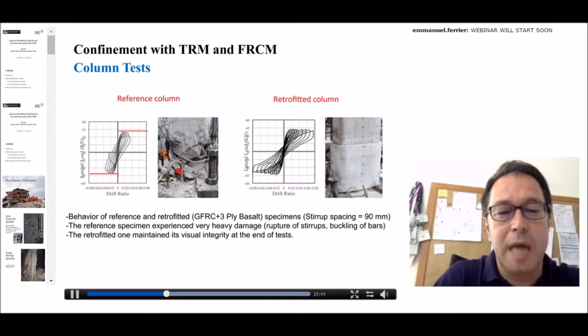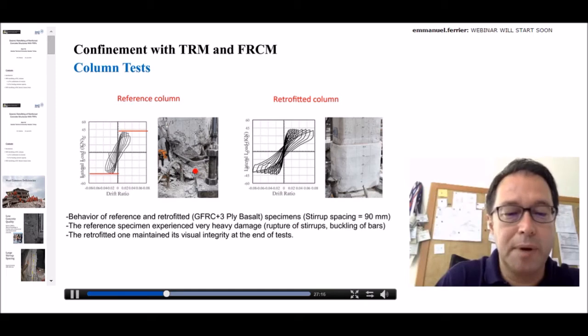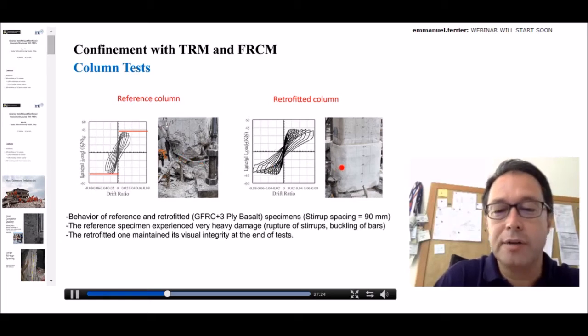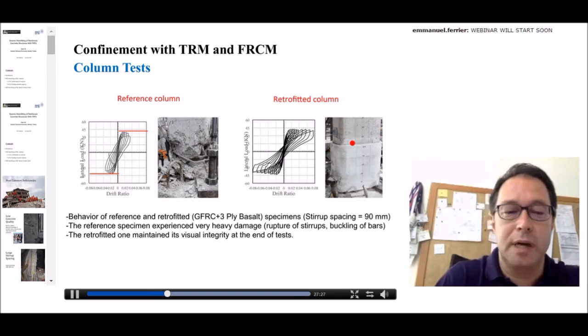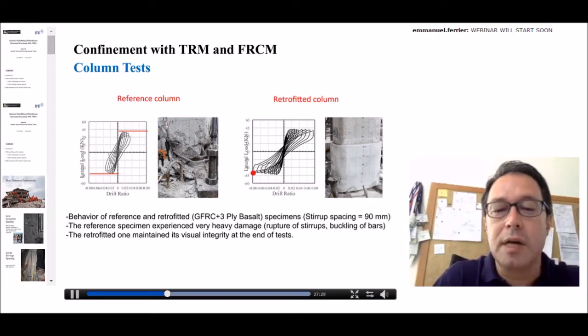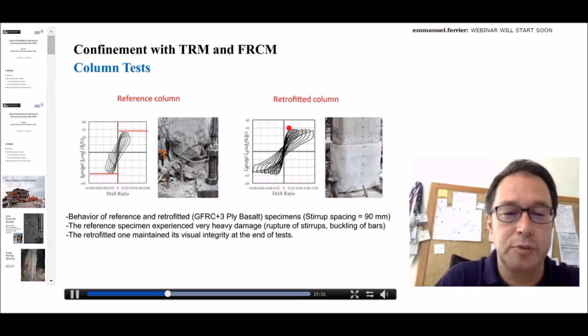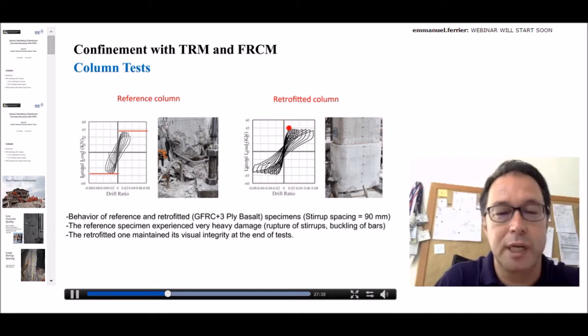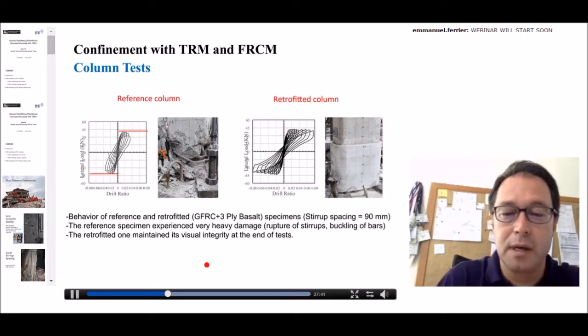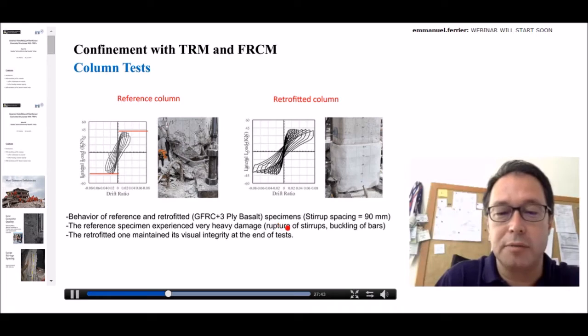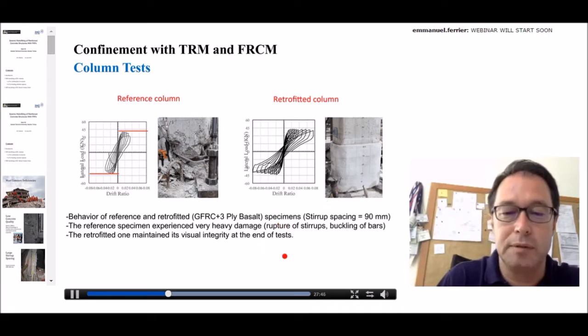So I think I already described the damage of reference specimens with rupture of stirrups, buckling of main bars, and total demolition of concrete after loss of this transverse reinforcement. On the other hand, this specimen retrofitted with this kind of jacket maintains load resistance capacity up to somewhere like 8% drift ratio, which is quite high for a typical earthquake, even for a typical severe earthquake. A severe earthquake could demand this from a typical reinforced concrete frame structure.